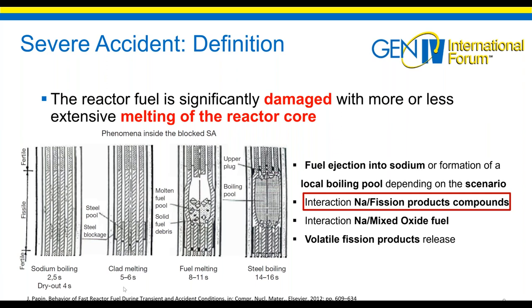And just a few seconds later, you have the clads, the barrier between the sodium and the fuel, that will start melting. And then only 10 seconds after the beginning of the accident, the fuel will start melting and end up with what we call a boiling pool, where after only 15 seconds, the steel will start boiling. So depending on the scenario, you can have this type of boiling pool or fuel ejection into sodium.